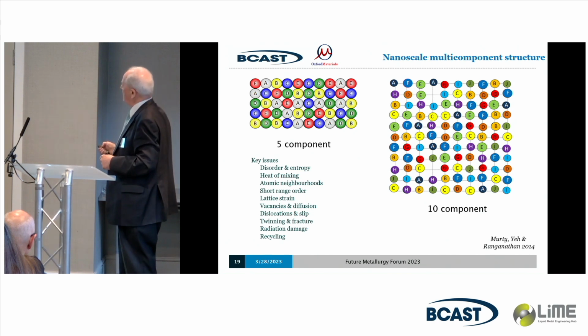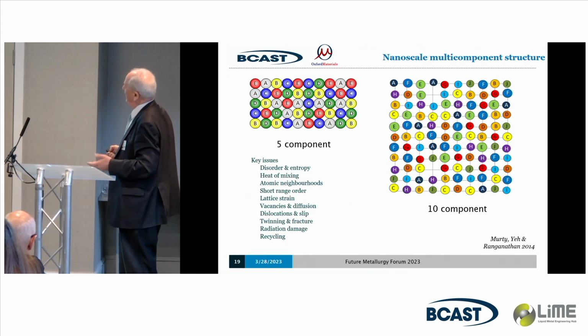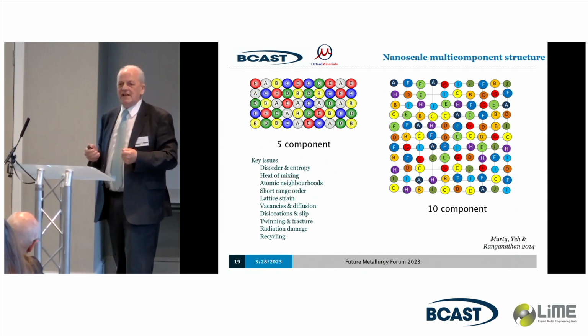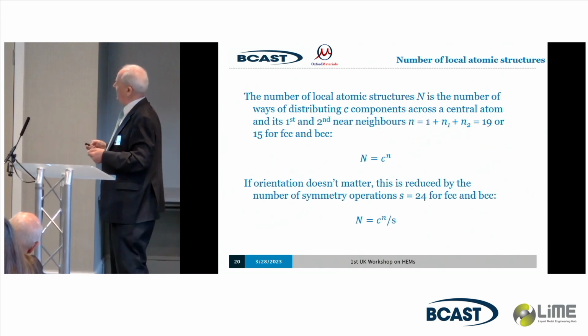Now, I wanted to talk very quickly in the last 2 or 3 minutes about the local structures. So here is a schematic of a 10-component system. And of course, unlike pure copper or pure iron or something, or pure silicon, the properties at each point are different because there's 10 different atoms. But it's more complicated than that, because around each C atom, the properties depend upon the local near neighbours. So this C atom here has different properties to this C atom because its near neighbours are different. And the first and second near neighbours have an effect.